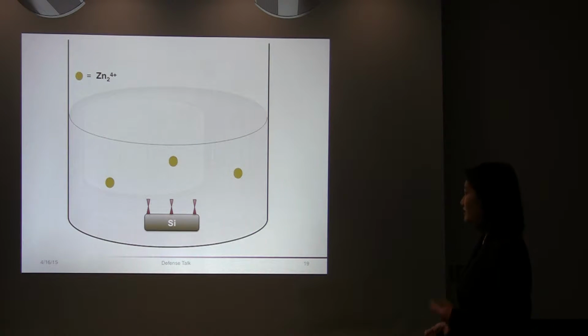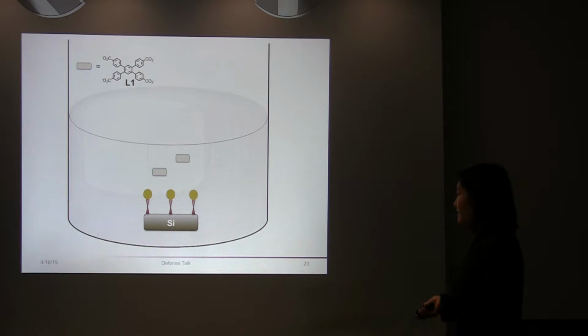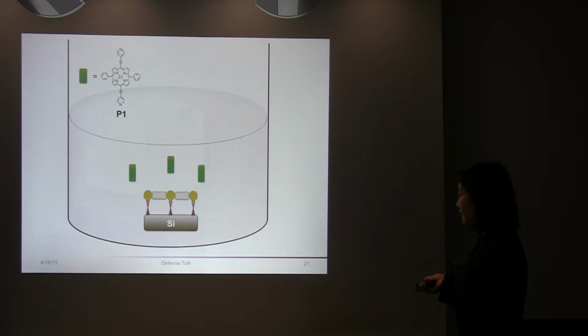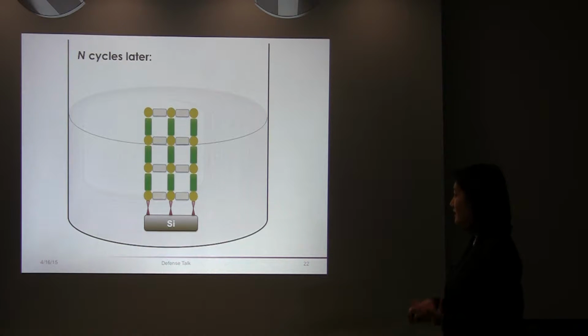Now let me introduce to you how this process actually works. So a pre-functionalized substrate, mainly an amine-terminated silicon substrate, recruits these zinc 2+ ions, and subsequently, to charge balance, these tetracarboxylate linkers are coordinated to the equatorial positions of the zinc paddle wheel units, followed by coordination of this dipyridyl porphyrin linker to the axial positions of the zinc 2+ paddle wheel units. And as a result of n number of cycles, you essentially get a film of homogeneous growth.